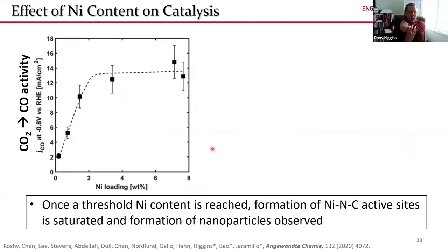Then we wanted to understand the impact of how much nickel we put in during the syntheses. So we started at very low nickel contents used during the syntheses, and we systematically ramped that up all the way from about 0.1 weight percent of nickel used during synthesis to about 8 weight percent. And what we found is that when we steadily increased the amount of nickel that was used during synthesis, we increased the activity for converting CO2 into carbon monoxide up until a point. And at that point, we saw a plateau. We no longer had a benefit from putting more nickel into those catalysts.